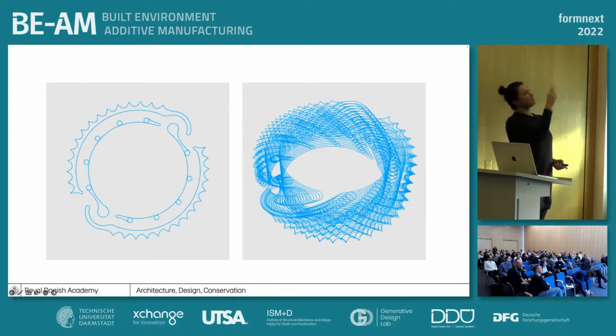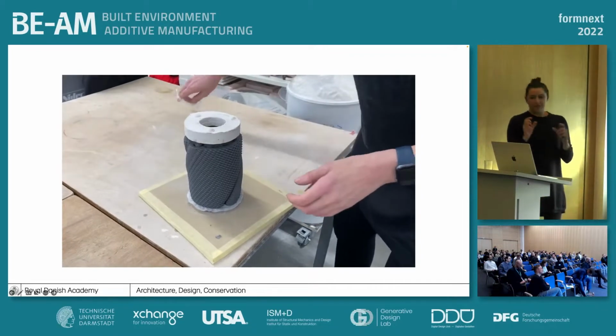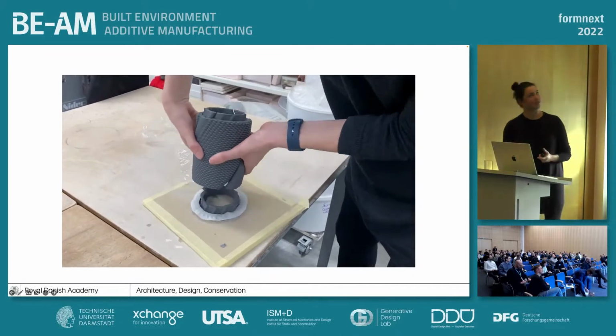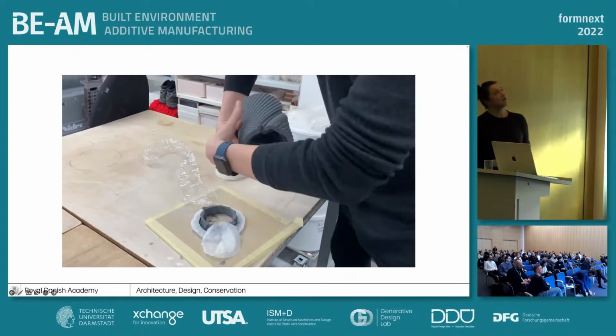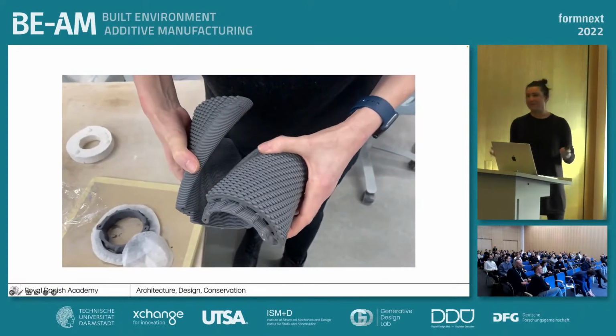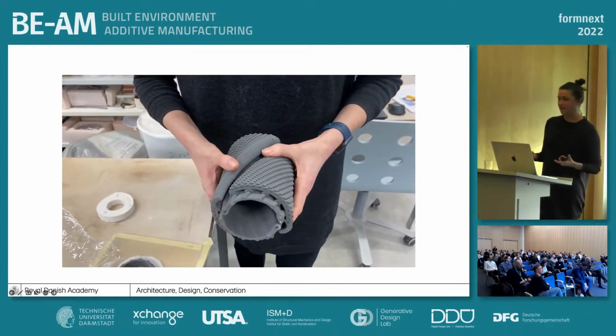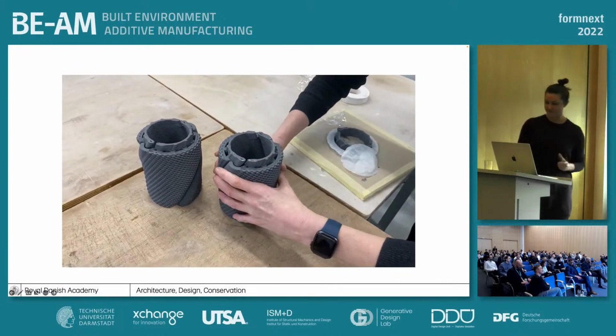But the adjacent pieces are printed at such a position that they're very lightly fused together. As the ceramic dries and becomes leather hard, after about 24 hours, you can take the pieces apart and gently crack them, and then reassemble them and put them into the kiln, fire them together. When you've got them as your final element, they're a very good fit, and you get a really good fit around the steel.